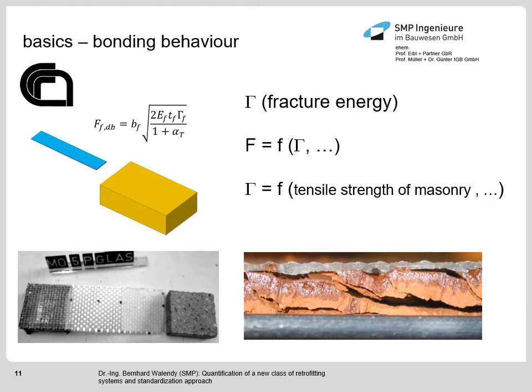Here, as it is shown in the down left corner, the load carrying substrate and the retrofitting system, the seismic wallpaper. You can see there was a decoupling and it was an adhesive decoupling. And that is why the formulas provided in most regulations cannot be used for the quantification of the seismic wallpaper, as we don't have this brittle cohesive failure, and that's why the formulas for the quantification of the fracture energy cannot be used. So an alternative approach has to be worked on, and I want to introduce this approach.